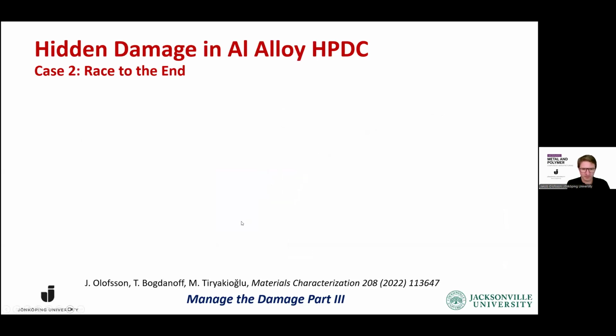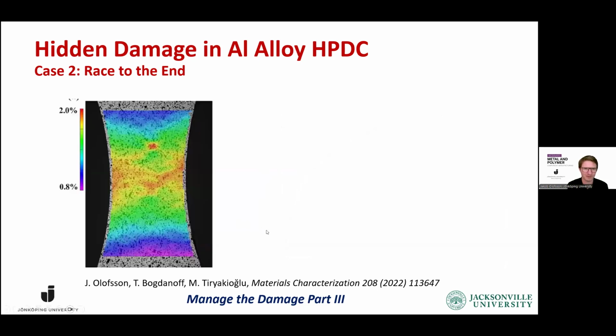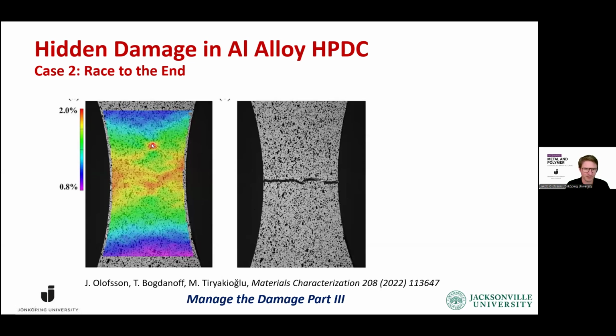The second group or case that we see is where the hidden damage is really fighting and competing all the way to the end. So here we see at the low load that, well, it's not as nice as you would see from the FEM simulation. There's something going on in the center here. There are 2 areas here that are really competing with the geometrical effect that we have. And also a bit higher up, you can see that there's a clear red spot, which is also causing a high strain locally in the material.